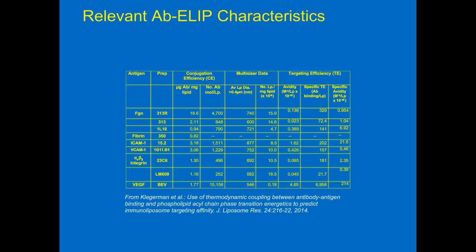We use a composite standard curve, which is what I showed, which is a curve that is reproducible. You have to use the same methods every time, and then you have an equation, and you use this to quantitate. Using these methods, you then make secondary standards which you can store, and then just use those. But periodically, you might want to re-standardize with another radio-labeled preparation. So that's how we did that.